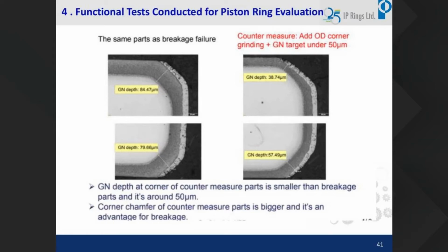But there were no changes in the process. It was developed and sent to the customer for testing. During testing, out of some 20 engine tests, we found that in a few engine sets the top ring broke and failed. So we made a deeper analysis. Why is such failure happening only in BS6 when compared to BS4? We came to know that in the BS6 application the thickness is reduced, but the pattern remained the same. Generally we do a gas nitriding process, which we call a pattern or a recipe, and earlier it was 84 microns.